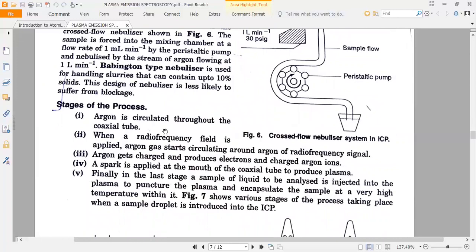stages of the process. Argon is circulated through the coaxial tube. When a radio frequency field is applied, argon gas starts circulating around the radio frequency signal. Argon gets charged and produces electrons and charged argon ions. A spark is applied at the mouth of the coaxial tube to produce plasma. Finally, in the last stage, a sample of liquid to be analyzed is injected into the plasma to puncture the plasma and encapsulate the sample at a very high temperature within it.